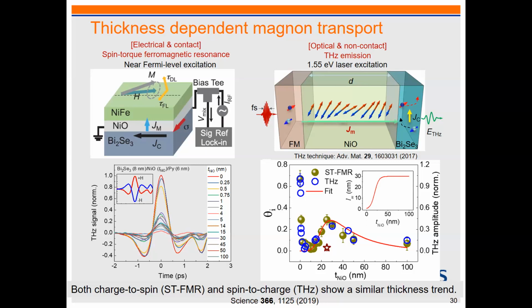As soon as we add any thickness of nickel oxide, the spin efficiency drops to almost 0, which kind of makes sense because you have some kind of oxide. Why can't spin current propagate along this vertical direction? Because it can't just go through. But when we increase the nickel oxide thickness to more than 10 nanometers, we start to see an increase of this spin efficiency, which has a peak at about 25 nanometers, and then the efficiency is about 0.3. This is the effective spin angle. So how come 25 nanometer thick nickel oxide can support spin propagation? The only possibility is magnons.